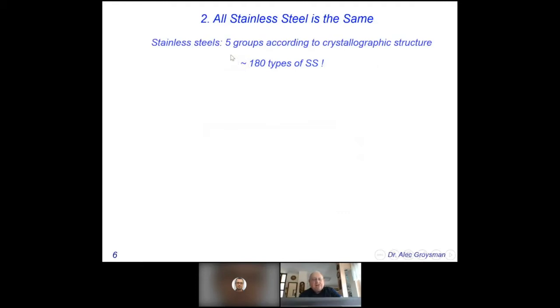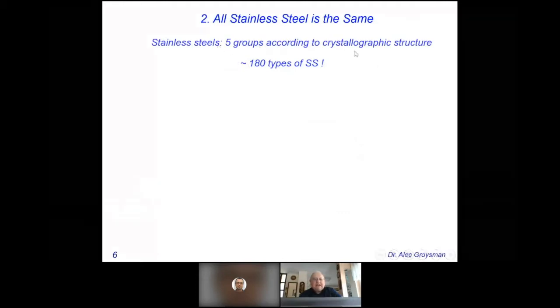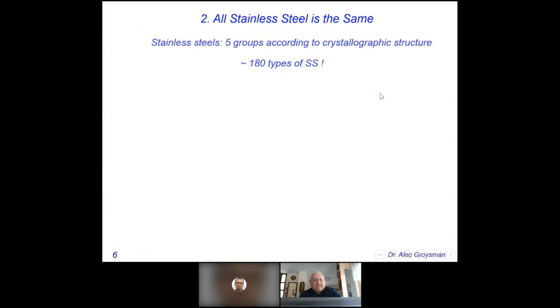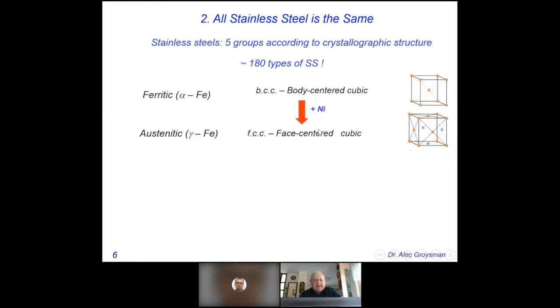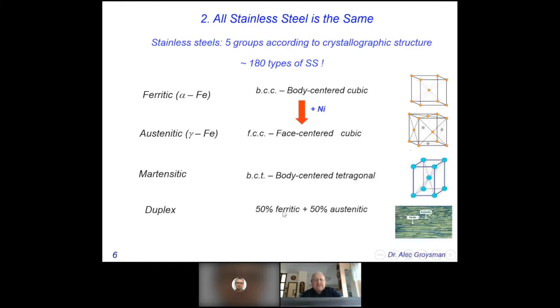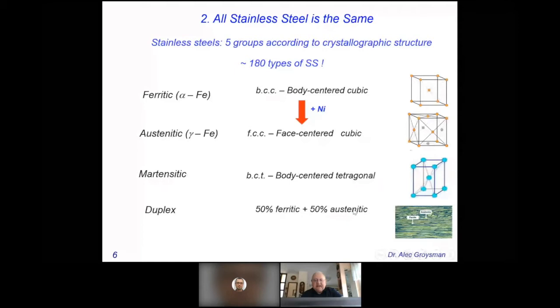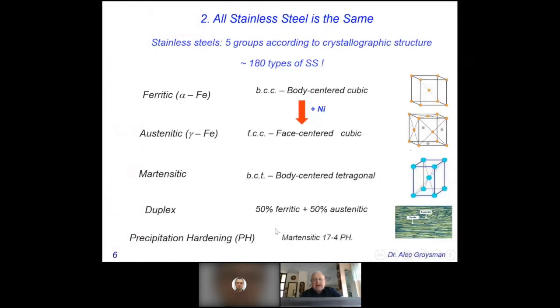There are 5 groups according to crystallographic structure and about 180 types of stainless steel. Ferritic with body-centered cubic, when adding nickel; austenitic with face-centered cubic; martensitic body-centered tetragonal; duplex 50% ferritic plus 50% austenitic; and precipitation hardening, PH, and each type has its own properties.